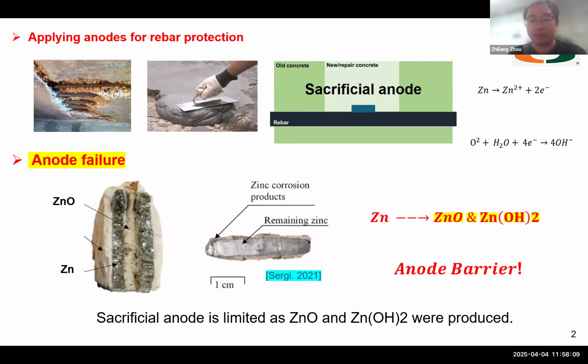You can see this phenomenon in these pictures, where the produced zinc oxide or zinc hydroxide can cover the anode surfaces as solid-state barriers. These barriers can stop the anode reactions. This is why the sacrificial anodes fail inside the concrete.